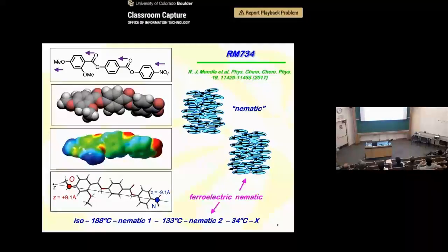Okay, so the second nematic turned out to be the ferroelectric nematic, and you notice here that all the dipoles are pointing in one direction. So now this phase is described by a double-headed vector field. This phase is described by a vector field, which tells you in space which direction this average long axis is, and the polarization density of the phase.